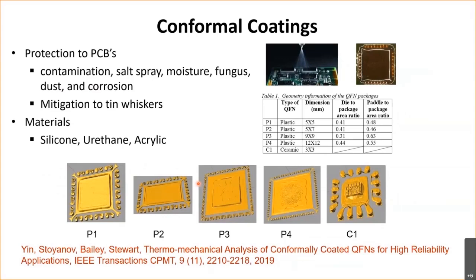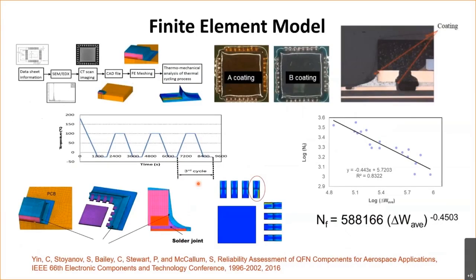There are different types of conformal coatings, silicone-based, acrylic-based conformal coatings. This is some work we did in looking at conformal coatings and the impact they may have on QFN type components. A lot of interest in QFNs, they're low standoff, but what is the impact of those conformal coatings on the solder joints? Again, COTS components, these would have been scanned, and all that internal construction of the component then goes into a finite element mesh where we can then do thermomechanical type simulations.